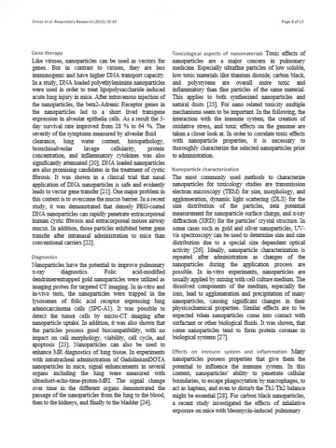In some cases, such as gold and silver nanoparticles, UV-Vis spectroscopy can be used to determine size and size distribution due to a size-dependent optical activity. Ideally, nanoparticle characterization is repeated after administration, as changes of nanoparticles during the application process are possible.